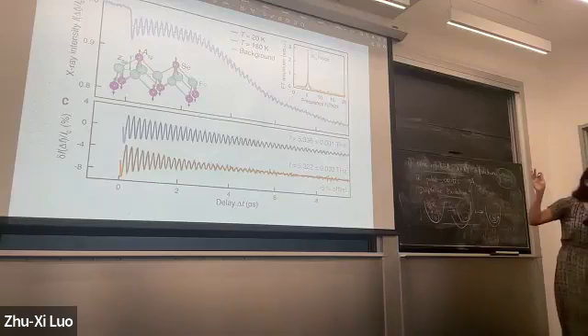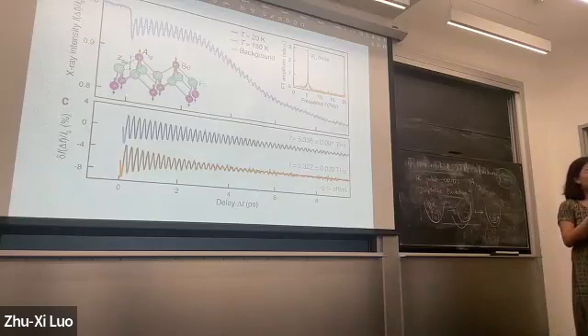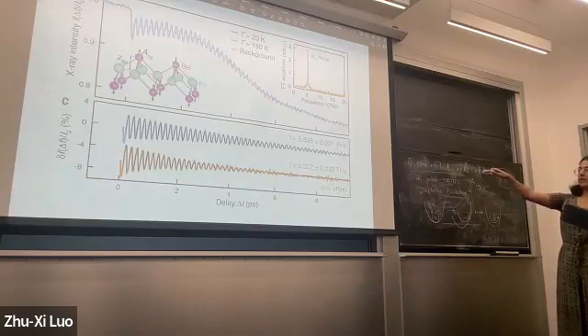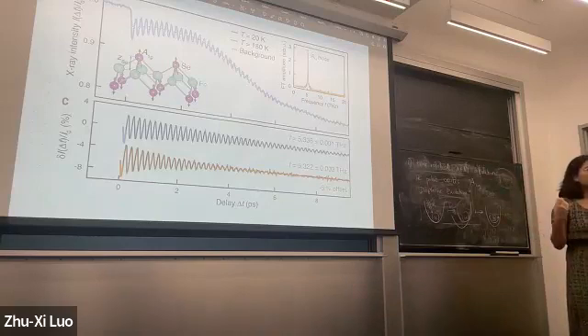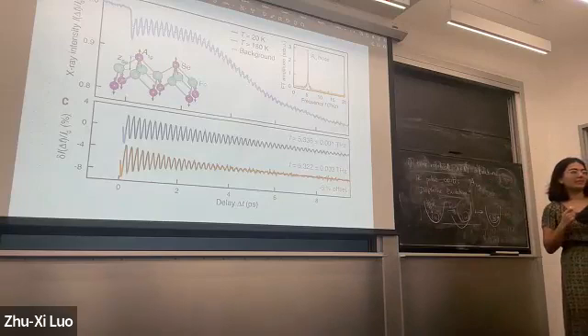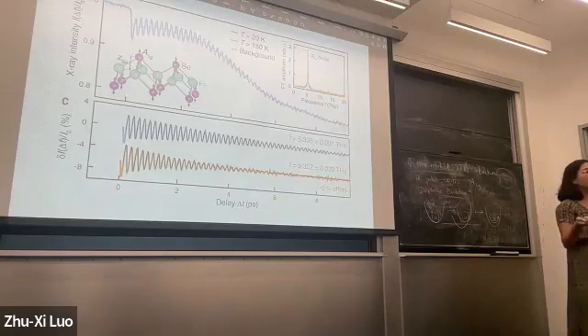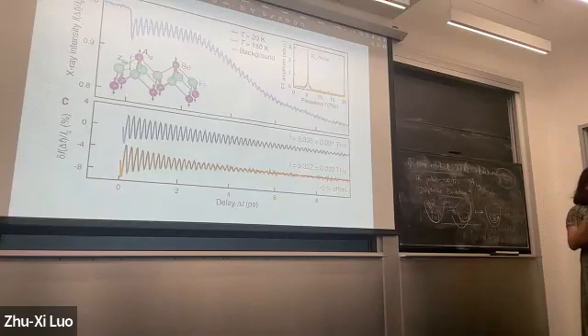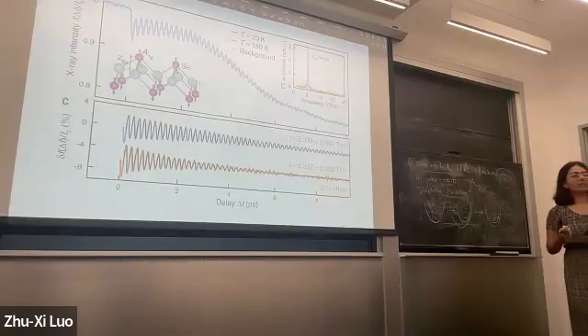And by subtracting away this background, because I think it's a generally well modeled background, you can fit this cosine more precisely and see that these oscillations are happening at exactly the frequency that we would expect for this particular phonon mode. And so this is good evidence for the fact that we've coherently excited this particular mode.